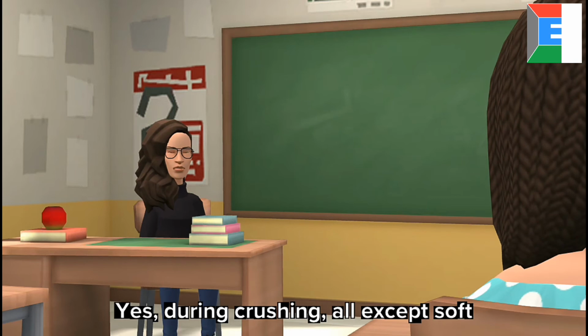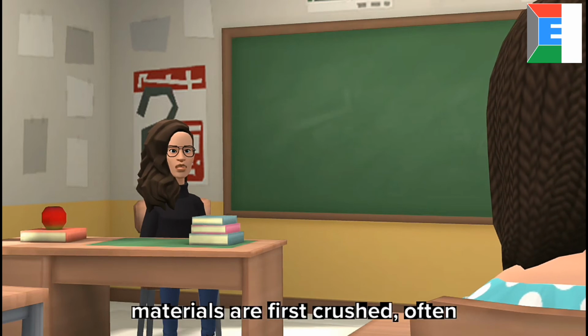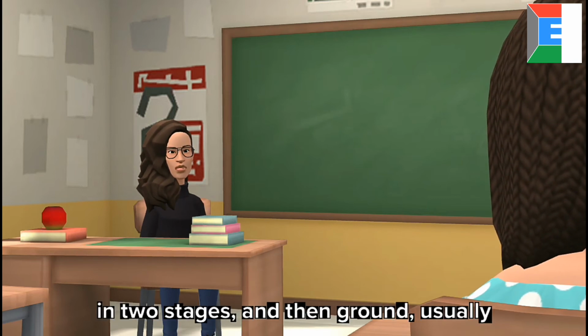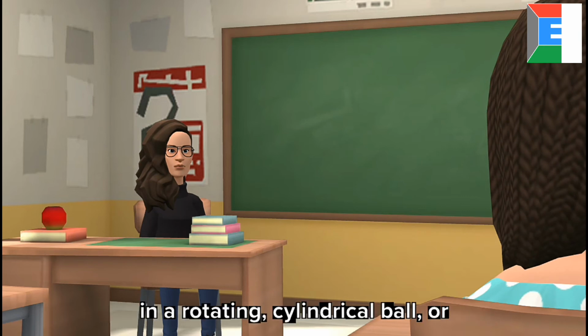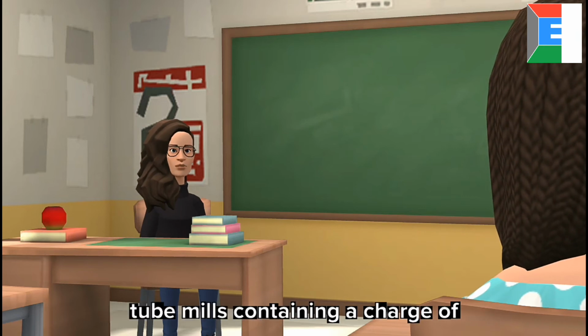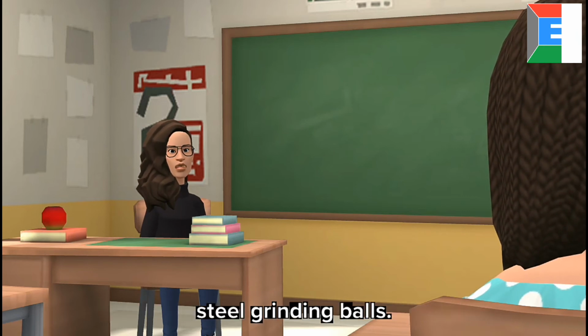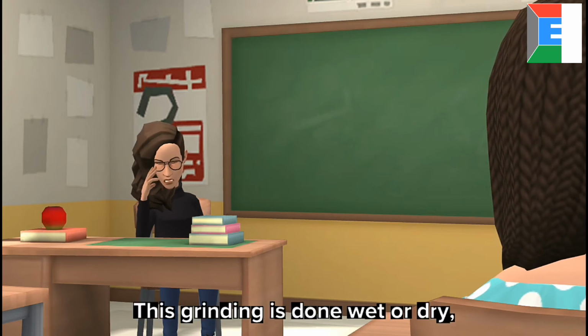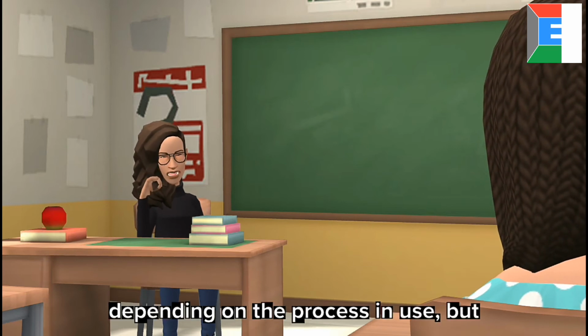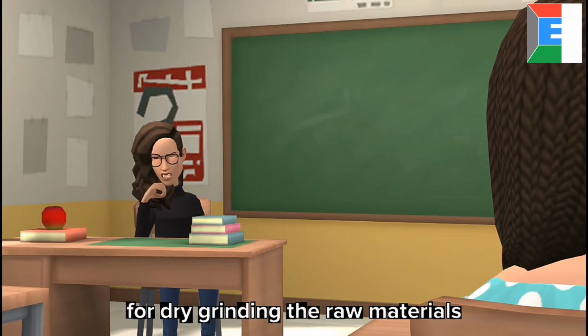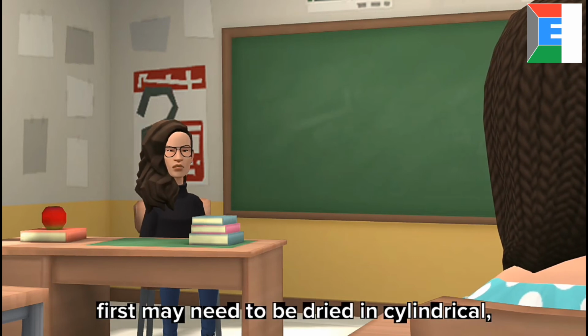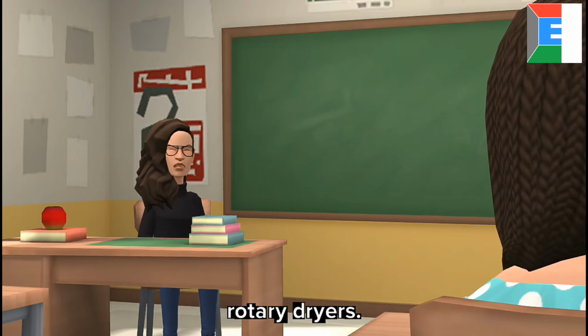Yes, during crushing, all except soft materials are first crushed, often in 2 stages, and then ground, usually in rotating, cylindrical ball or tube mills containing a charge of steel grinding balls. This grinding is done wet or dry, depending on the process in use, but for dry grinding the raw materials first may need to be dried in cylindrical, rotary dryers.